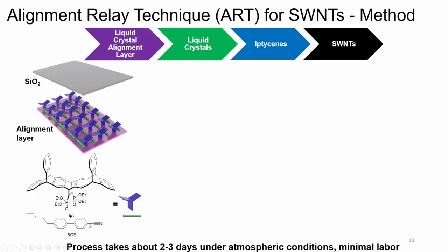So the ART method has the iptycene molecule, but it's dissolved into what is known as a liquid crystal. Liquid crystals have a high degree of alignment associated with them. We use 5CB in this case, but there are other forms and other structures. Liquid crystals align fairly readily depending on their environment and what type they are. Because of the nature of the liquid crystal, the alignment is being transferred onto the molecule, and therefore the position of the molecule is being controlled on the surface. So instead of having a self-assembled monolayer, or SAM, we're having a controlled assembled monolayer thanks to this methodology, manipulating the nature of the liquid crystal.